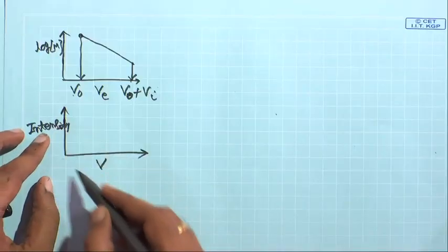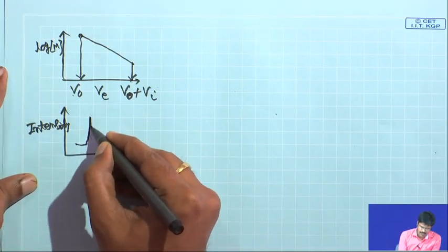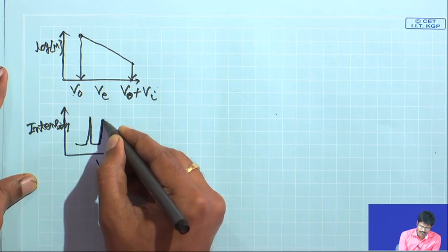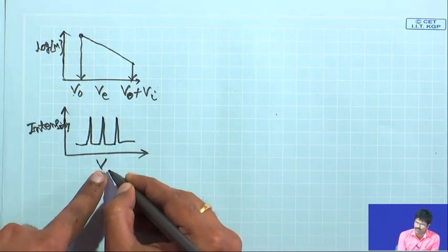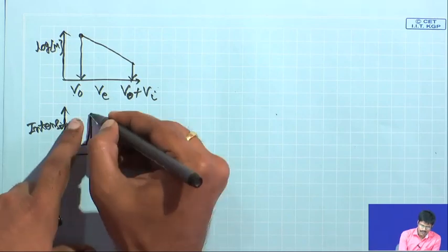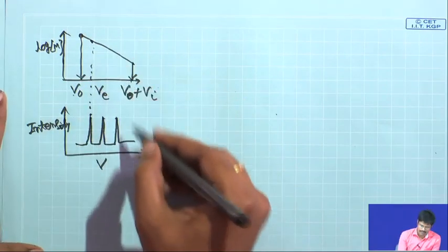If you plot intensity versus elution volume, suppose you have 3 different monodispersed samples. Depending on their molecular weight, they will come at different times or at different volumes. You can use volume or you can use time to construct this particular curve of log M versus V.